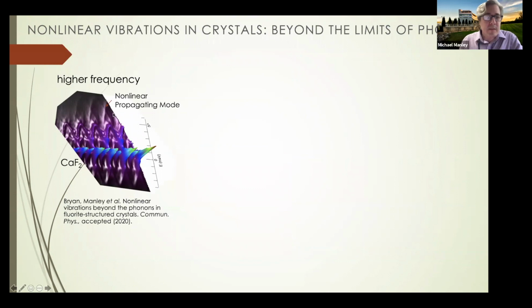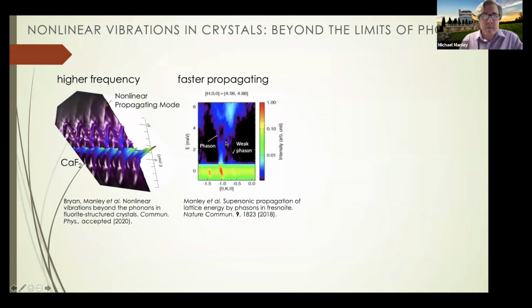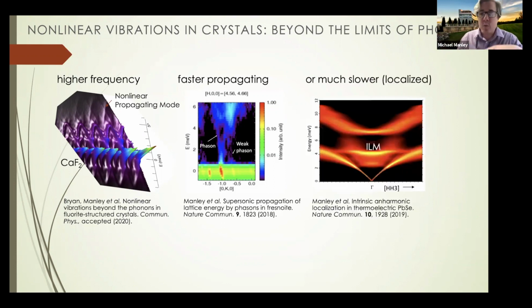This was a paper that's just been accepted, where we see nonlinear propagating modes in the dispersion that occur 40 to 60% higher than the maximum phonon frequency. And this is in fluorite, but we've seen them in every fluorite that we've looked at. They're always there. And so they're not phonons, they're nonlinear modes. I've looked at phasons, which are basically vibrations in a soliton lattice, and they're motions of atoms, but they're not translations, they're reconfigurations. In this case, they move 3 or 4 times faster than the speed of sound. So you can get some really counterintuitive things when you go nonlinear. And they do that because they distort the properties as they propagate through, kind of like warp drive. If you're a Star Trek fan, they warp space-time. It warps the material.